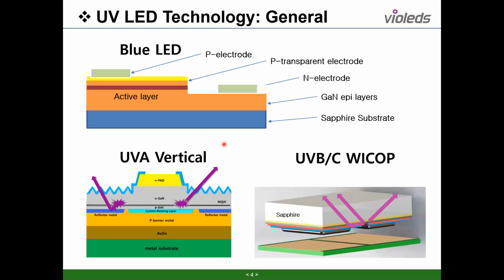The difficulty is removing the sapphire, which we call LLO, laser lift-off technology. The laser goes from the outside to the bottom, to the boundary between the sapphire and the gallium nitride, and the laser is absorbed by the surface of the gallium nitride layer. The gallium nitride band gap is much lower than the laser photon energy, so it is absorbed well, and then we can easily remove the substrate.